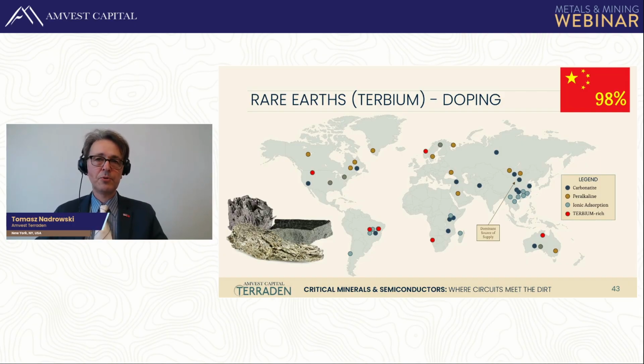So, for example, europium, which in itself is a phosphor. So, when excited with energy, electrons go to a higher energy level. When they go down, they start emitting photons. In the case of europium in the visible spectrum, that will be red color. In the case of cerium, the light lanthanide, that would be blue. But the same europium can be used to increase luminescence of chalcogens, so say tellurium, selenium, or sulfur. In the case of cerium, that would be zinc oxide or titanium dioxide.